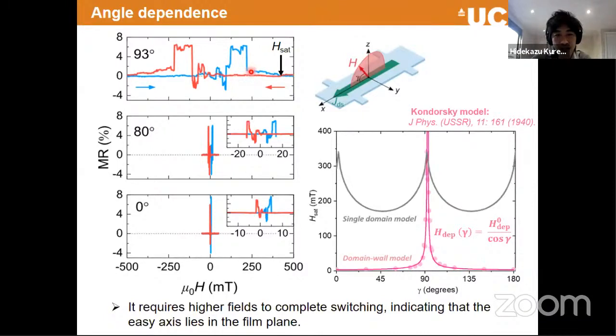Instead, what we take as an approach is that we decided to pick a point in the magnetic field where, when you apply the magnetic field back and forth, the resistance curves merge. We decided that this is the point where the external magnetic field fully compensates the internal magnetic field, i.e. the anisotropy. So we use this as a parameter to analyze our result. This is pretty much closer to out of plane.